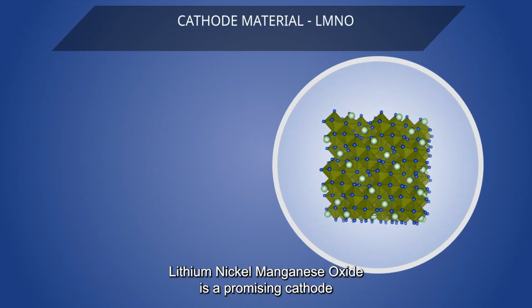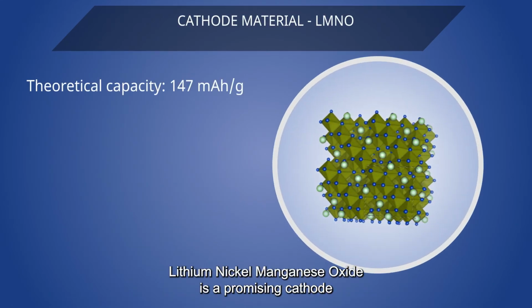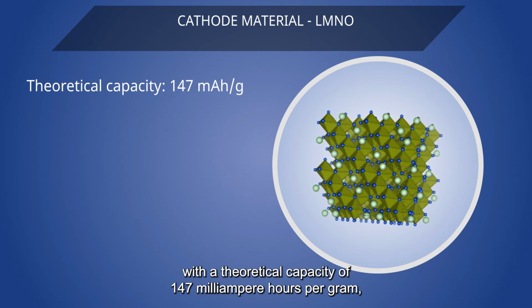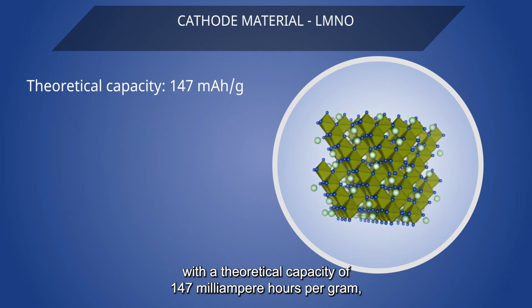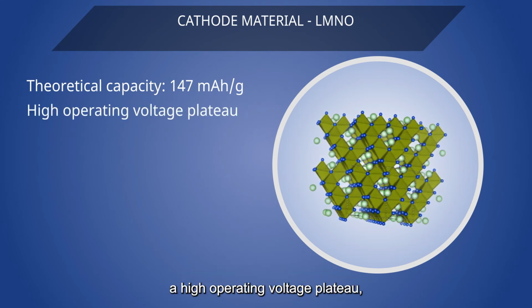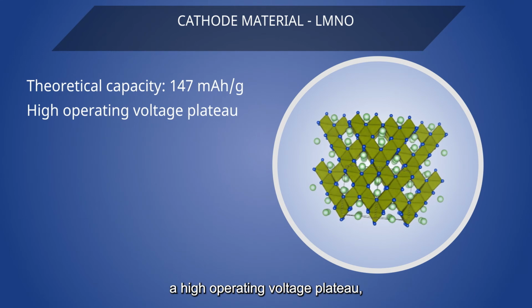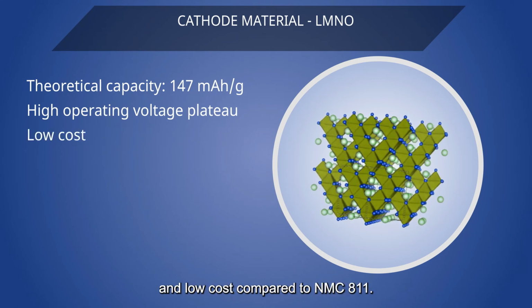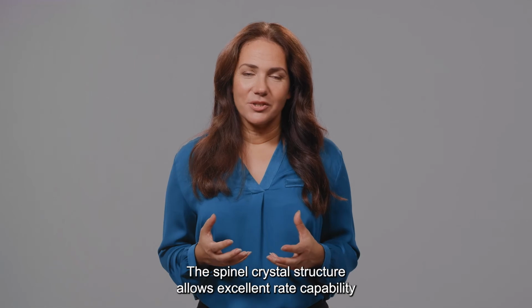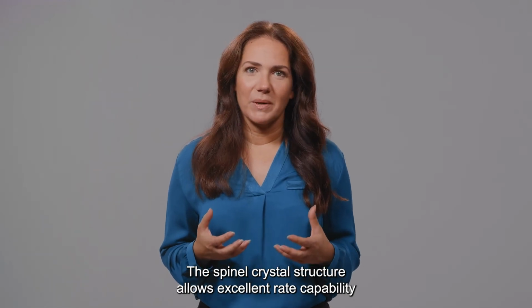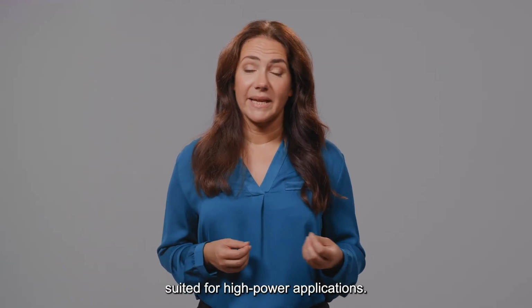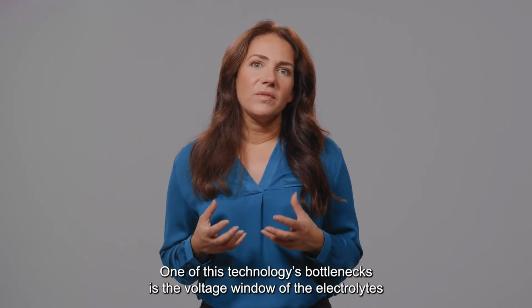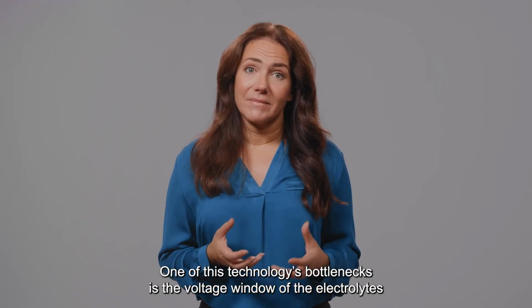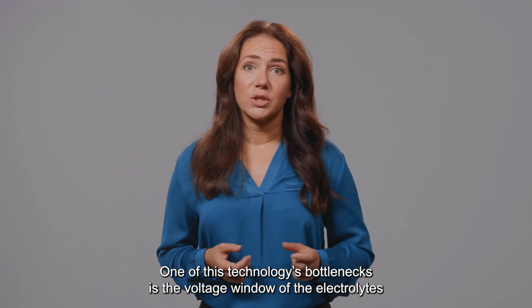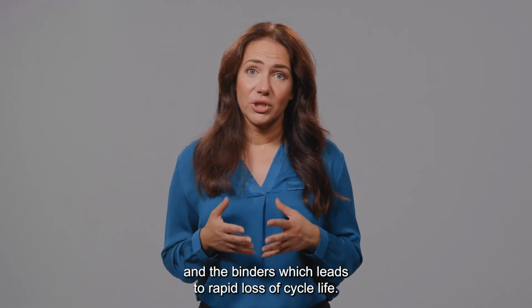Lithium nickel manganese oxide is a promising cathode with a theoretical capacity of 147 mAh per gram, a high operating voltage plateau, and low cost compared to NMC 811. The spinel crystal structure allows excellent rate capability suited for high power applications. One of this technology's bottlenecks is the voltage window of the electrolytes and the binders, which leads to rapid loss of cycle life.